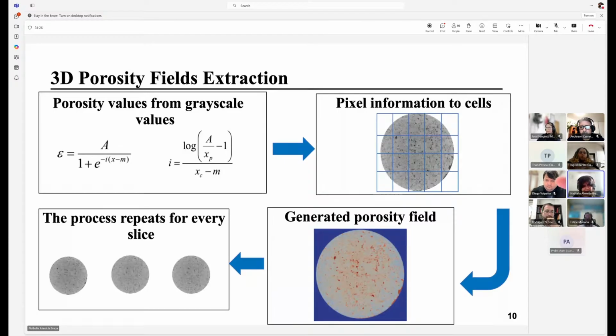we measure the mean of all these values in the same area, and this value turns out as the value of porosity in that cell. We do that for all of the cells. We generate a 2D porosity field, and then the process repeats for every slice. Then with the field for every slice, I can stack them, the same principle used for the micro-CT, to form my 3D field.